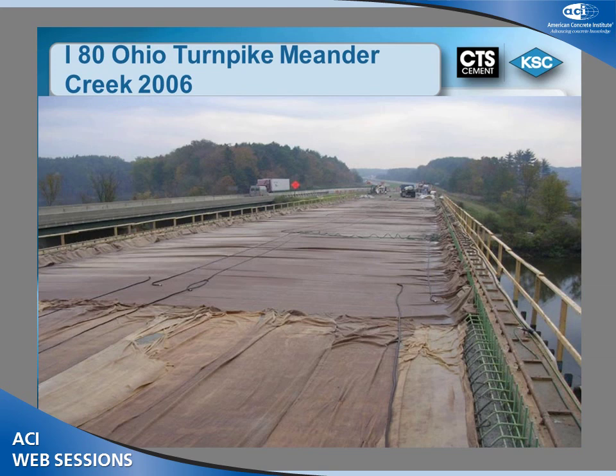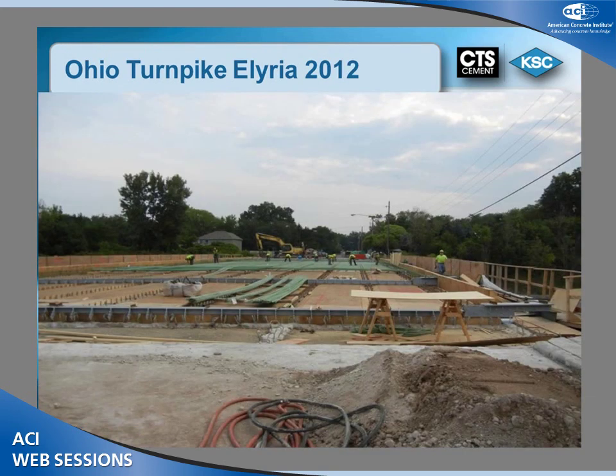Elongated sections. One of the things that we run into with shrinkage compensating concrete on bridge decks is that they're narrow and long. And we're not finding problems with that. We're not getting cracking in these decks, and it's a lot to do with the amount of restraint. If you think about it, you've got 2 mats of steel. It's a structural element. And so we're taking advantage of that in these structures. But this is not unusual. I believe this overall deck right here was right at 1,800 feet. It was poured all in one morning, okay? They had 2 ready-mix plants batching for this.